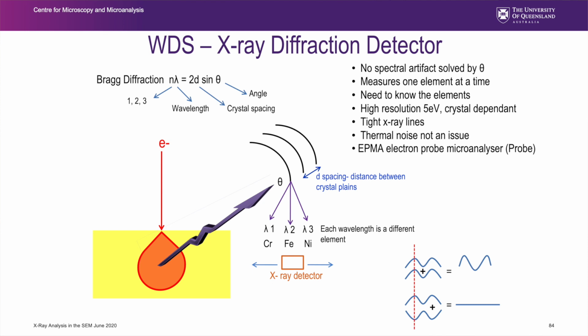These are crystals mounted off to the side. All the X-rays from the specimen hit those diffracting crystals, and each different wavelength gets diffracted in a different direction via the Bragg diffraction law. And we know that basically chromium goes in at one theta, iron goes at a different theta or angle, and nickel will go at a different angle again. So rather than try and work out the energy of my X-rays, I just use the diffraction effect and I go to the position where I know this is where iron will appear. And I know via diffraction, I count these as iron X-rays. Then I move my detector to another position where chrome will appear, and these are my chromium X-rays. And so forth for all the elements in the periodic table.